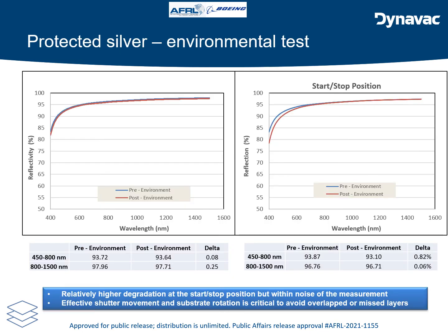Protected silver environmental test results. We did environmental tests on our standard set of protected silver coated samples. We particularly paid attention to the start and stop positions. As we discussed earlier, one of the likely places where non-uniformity could occur is where we start and stop deposition, that strip along the mirror. So we put glass coupons along that strip, and we looked at the reflectance and adhesion, and we also put the samples through stress test.